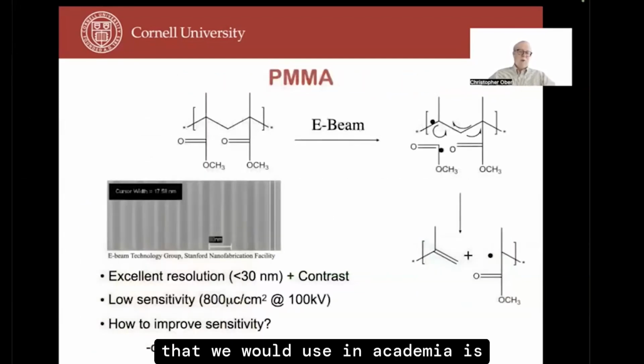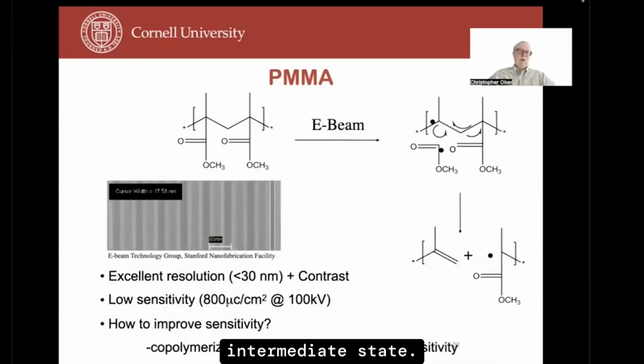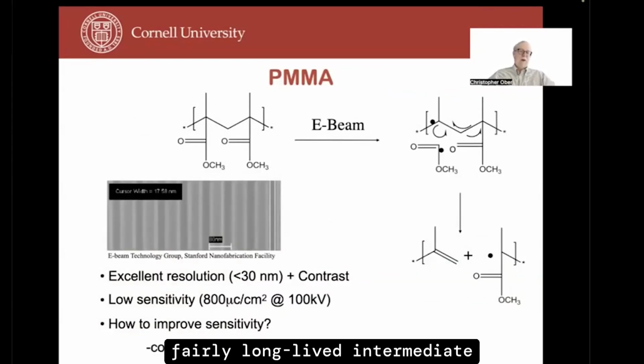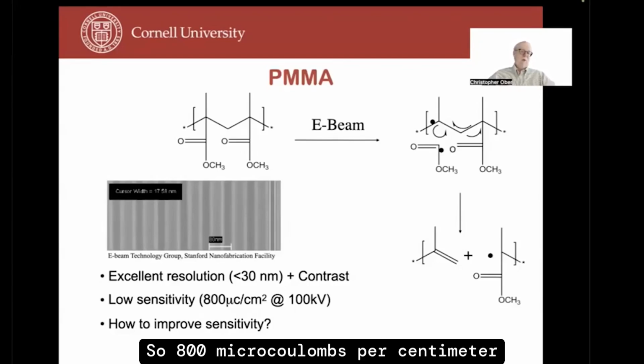The simplest resist, again, one that we would use in academia, is polymethyl methacrylate. What happens is when the electron beam hits the resist, it can be induced through bond breakage to go into a high energy intermediate state. And this particular polymer has a fairly long-lived intermediate state. And so that enables, instead of simply cross-linking, depolymerization to occur. And so it is a low sensitivity system. 800 microcoulombs per centimeter squared is a typical sensitivity, which means it's not very sensitive, but it can give excellent resolution. And with a superior system, it's possible to get certainly below 30 nanometers.